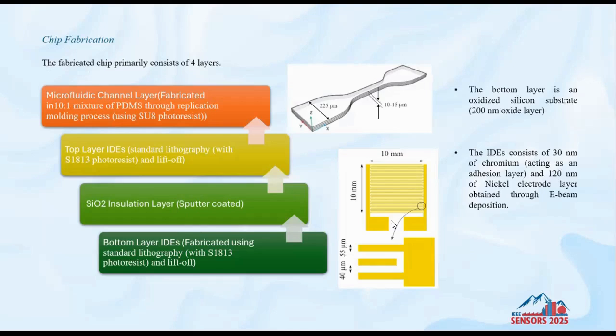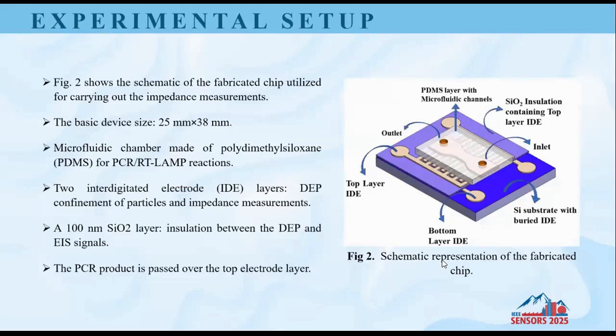Okay, so the bottom layer is an oxidized silicon substrate, which contains a 200 nanometer oxide layer, and the IDEs are of 30 nanometers of chromium and 120 nanometers of nickel electrodes, making the whole chip a very inexpensive device. Moving ahead with the experimental setup, the schematic shown here actually represents the whole chip structure.